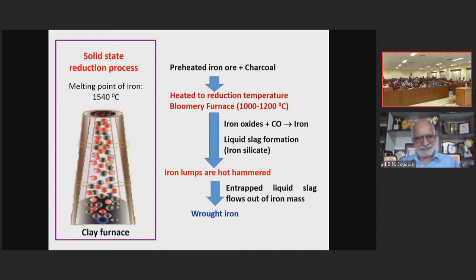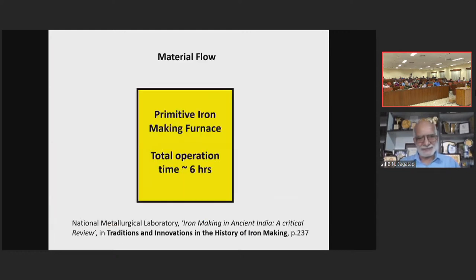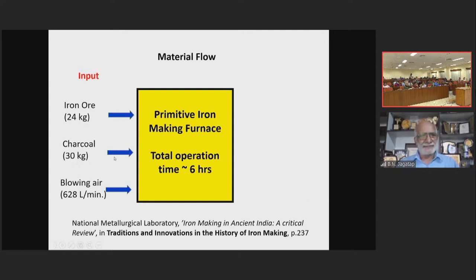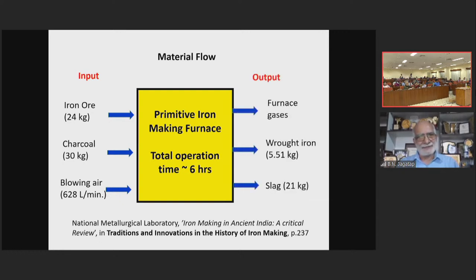Now, this is the practice of these ethnic groups, and it has also been studied. You take a typical primitive iron making furnace, with a typical operation time of 6 hours. You have 24 kg of iron ore, and then pour 30 kg of charcoal and blow air at 628 liters per minute. And you can see the output. You have the furnace gases, then wrought iron and the liquid slag. So you take 24 kg of iron ore. At the end, you get 5.5 kg of wrought iron.